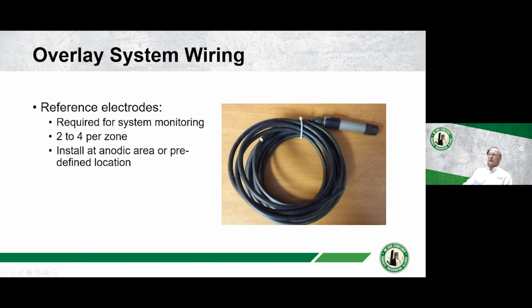Your reference electrodes, this has a cap under here, and under this is a ceramic tip, and these reference electrodes get drilled and grouted into the concrete surface. And you normally have 2 to 4 per zone. Sometimes you can have as many as 8. It all depends on how you're going to monitor the system.